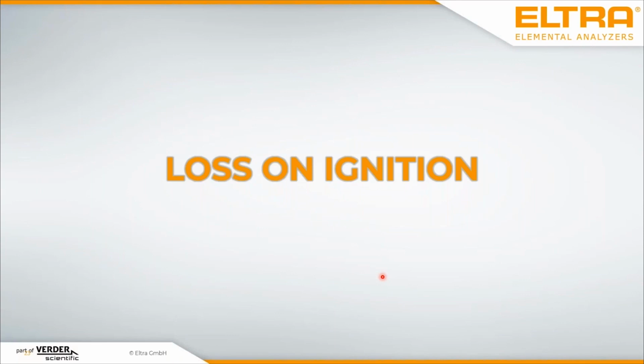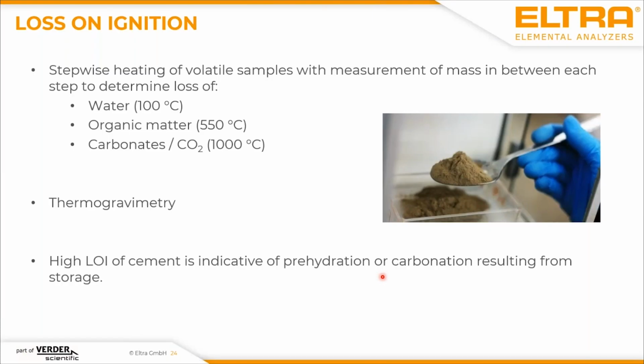This is a bit of a misleading word, but it is more or less what we have in the literature. It is a phrase which was mainly thought for coal, where you really ignite something. Cement, of course, you don't ignite, but nevertheless, this is the phrase we have in the literature. So what you do is you take your sample, your cement sample or limestone sample, it doesn't matter, and then you stepwise raise the temperature, and during the temperature raise you look at the mass of your sample.